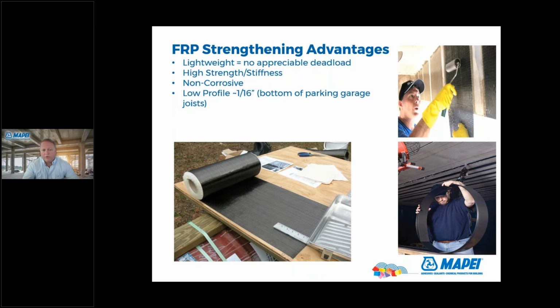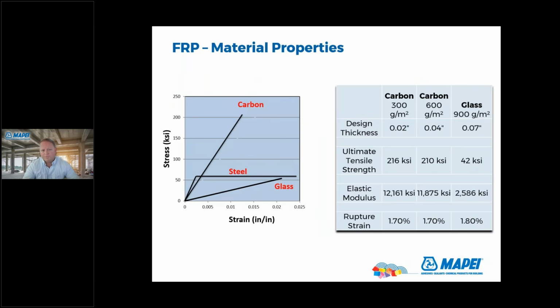It has a very low profile, very thin. Great application on the bottom of parking garages, on the bottom of joists, where you can't add a lot to the cross section because you have trucks driving in there and everything else. There's a fast installation and cure time. Typically, by the time you put it up, 24 hours, the system's cured, your structure's strengthened. And then also very minimal equipment. You don't need heavy equipment. You see a roll of fabric. You see this gentleman just kind of carrying some of this material, buckets of epoxy. So minimal equipment required to do these projects. So some FRP material properties.